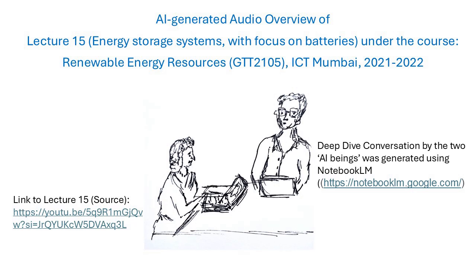And because lithium is so electropositive and fluorine is so electronegative, boom, high voltage, around 3 volts, way higher than aqueous cells. But again, primary. That LiF formation was basically irreversible, couldn't recharge it easily. But conceptually huge. It showed lithium plus non-aqueous electrolyte equals high voltage. The potential was clear, even if rechargeability wasn't there yet.